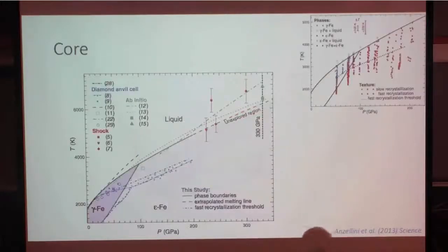And from the core side, what you need to know, first of all, is the melting point of iron. Jackie showed this figure from this paper already. Here's the data. They go up to 200 GPa. It's a very nice technique where they do X-ray diffraction, and they have positive identification of melt from the X-ray diffraction from diffuse scattering. Very nicely done.